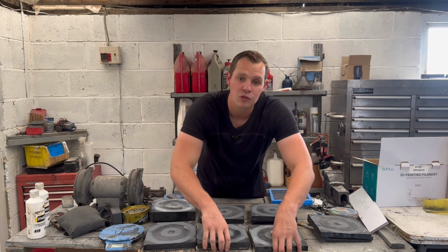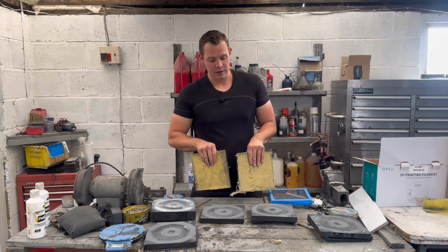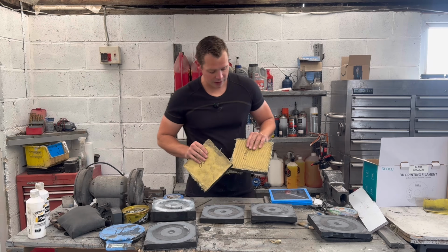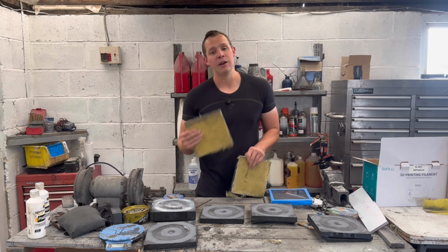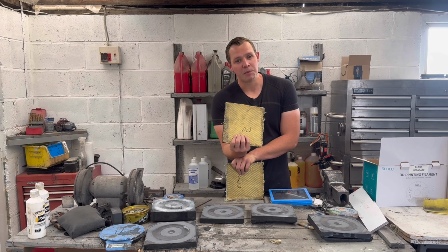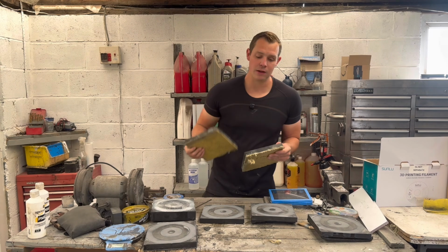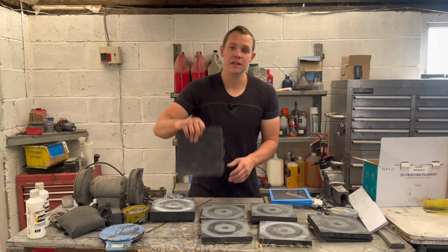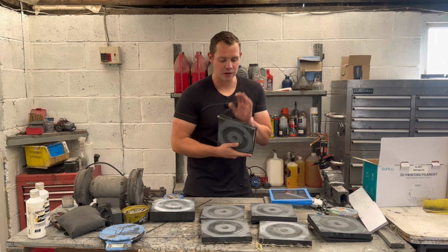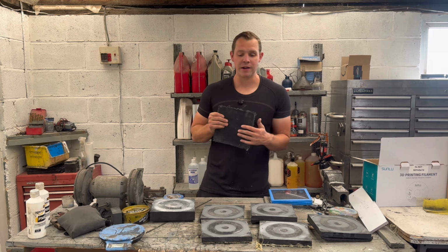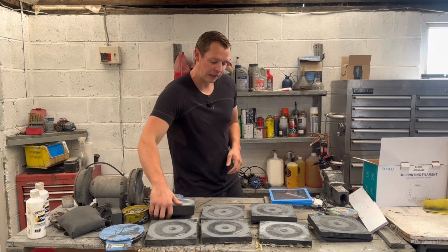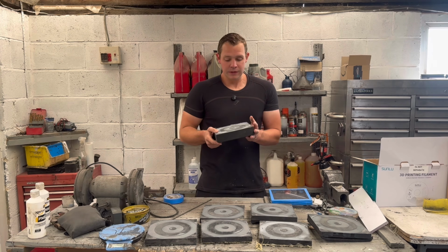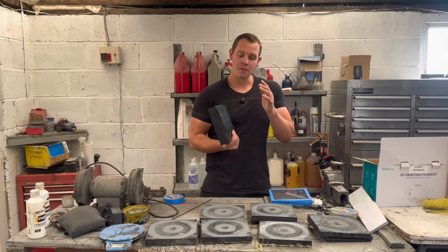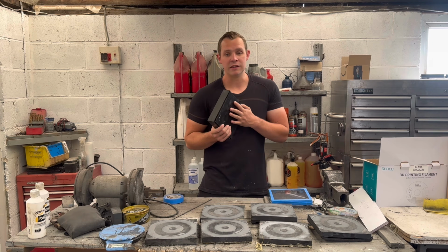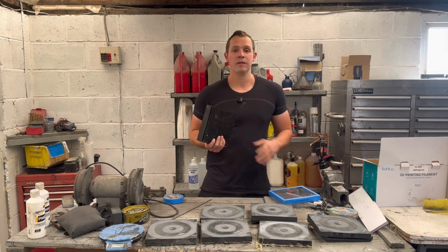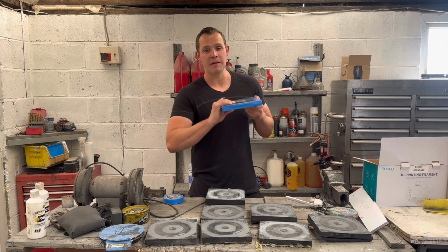And then we have the 2 pieces, both with 2 layers of ceramic added on with Kevlar, but one with the epoxy resin and one with the soft resin, that being the polyurethane resin. And then to make a good comparison, we also have the denim, which is 2 layers of ceramic with the layers of denim on the back, good comparison against Kevlar. And then finally we have the thick plate with the 4 layers of ceramic, polypropylene on the back, as well as the little sheet of metal as well. And of course the glass we've just looked at.